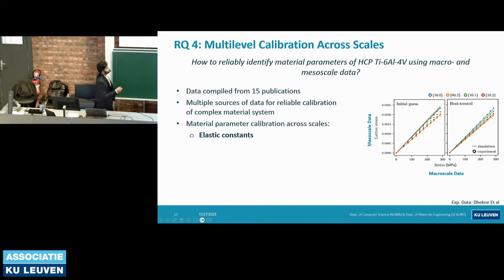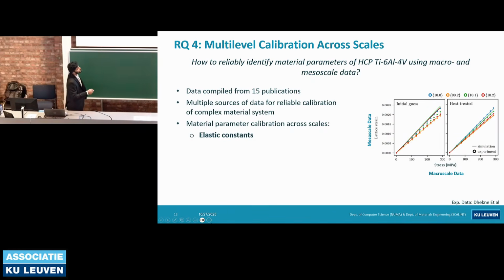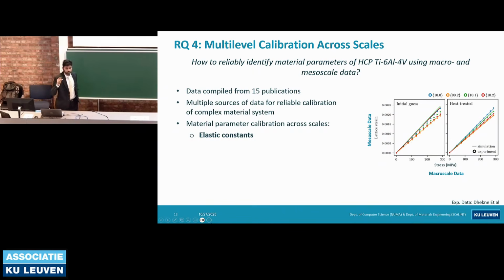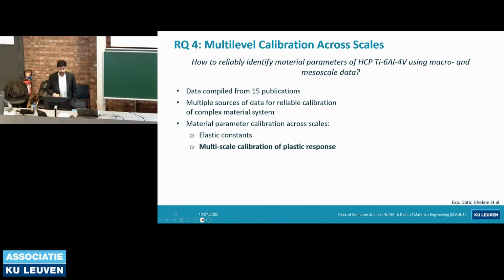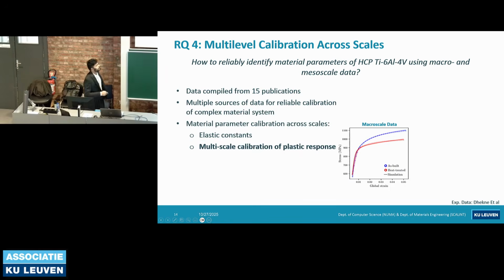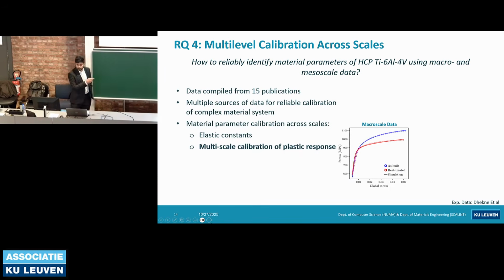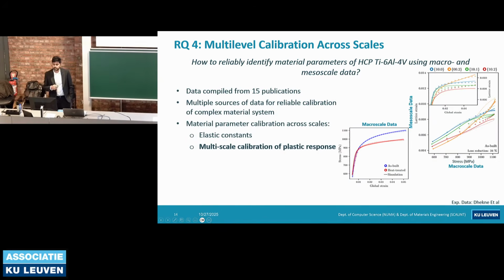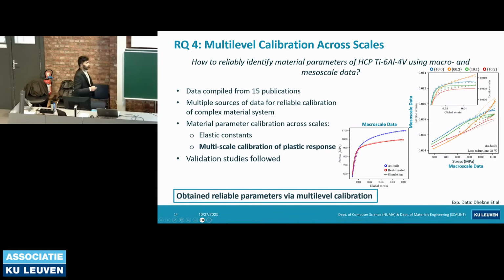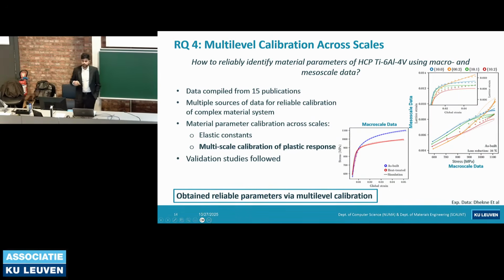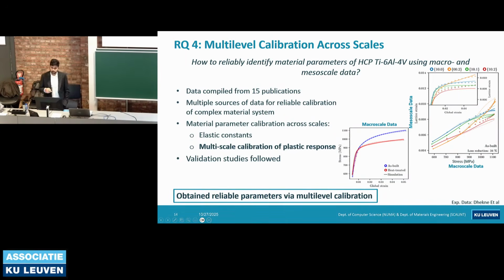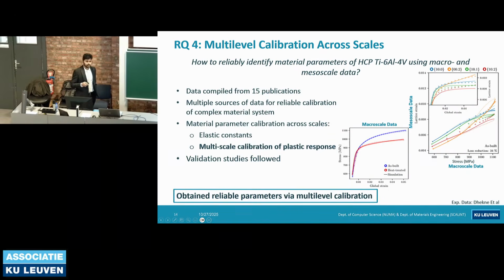I just wanted to show that we have mesoscale data, macro scale data and experimental data which are scattered, and then, using an optimization algorithm, we fit the data and obtain elastic constants. Similarly, for plastic response, we fit the model not just at macro scale, but also with the mesoscale and macro scale data sets. With these reliable parameters, we also performed validation studies. So what we obtained from this is reliable parameters for hexagonal close-packed titanium via multi-scale calibration.